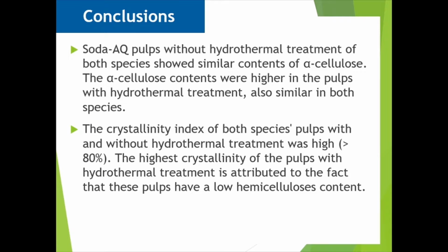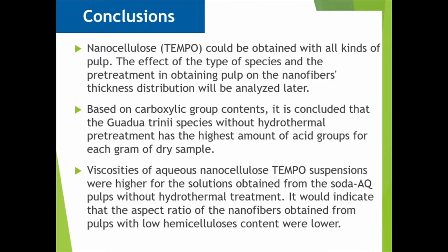Soda and anthraquinone pulps without hydrothermal treatment of both species presented similar alpha cellulose contents. The alpha cellulose contents were higher in the pulps with hydrothermal treatment, also similar in both species. The crystallinity index of both species pulps with and without hydrothermal treatment was high, more than 80%. The highest crystallinity of the pulps with hydrothermal treatment is attributed to the fact that these pulps have a low hemicellulose content. TEMPO nanocellulose could be obtained with all kinds of pulp.